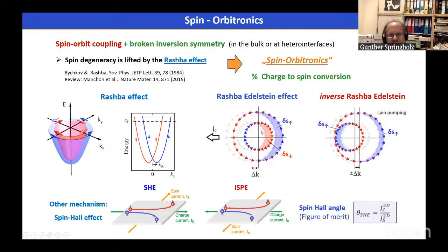Another mechanism that is also based on the spin orbit coupling is the so-called spin Hall effect. So if you pass a current through a system with a large spin orbit coupling, then there is an asymmetry in the scattering of the electrons as a function of spins. So electrons with spin up are slightly more probably scattered in one direction than the electrons with the spin down orientation. And this gives rise also to a spin separation. So the up spins will go to the upper side, and the down spins preferably to the lower side in this diagram. So in this case, we have a charge current and a spin current that is perpendicular to the charge current.